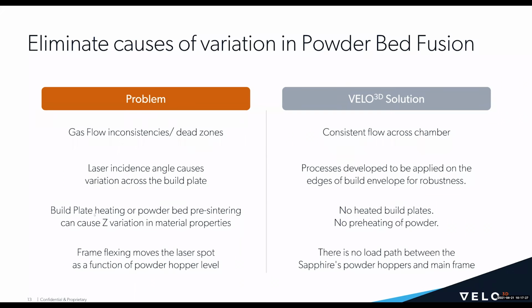Next, commonly there's build plate heating, powder bed pre-sintering, or build chamber heating that occurs in other systems. This can cause variation in the Z direction with material properties. You get larger grains towards the bottom and smaller towards the top. At Velo3D though, with our Sapphire, there are no heated build plates and no preheating of powder. We do this in order to drive uniformity throughout the build volume.